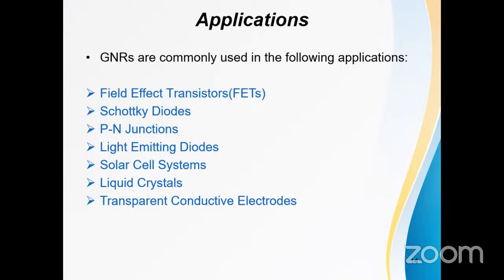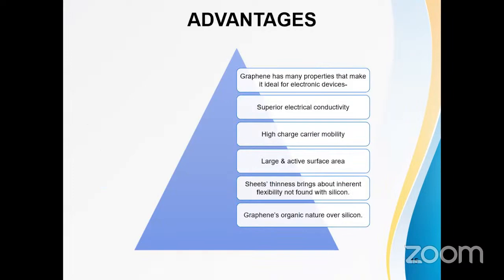The mechanical properties of the two most common graphene nanoribbons, zigzag and armchair, were investigated by computational modeling using density functional theory, molecular dynamics, and the finite element method. Here are the various advantages of graphene nanoribbons over other semiconducting materials like silicon. Graphene nanoribbons have many properties that make them ideal for electronic devices, like superior electrical conductivity and high charge carrier mobility.